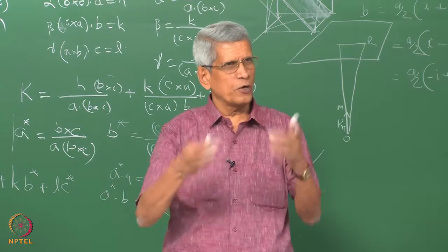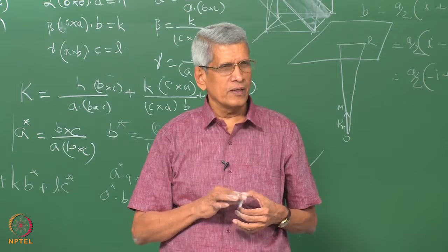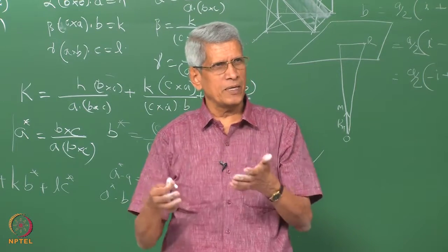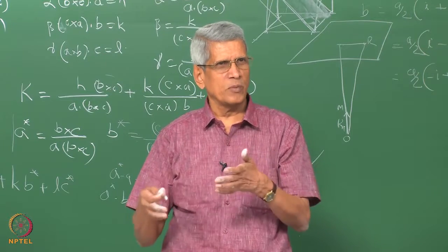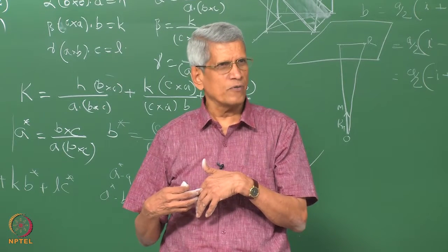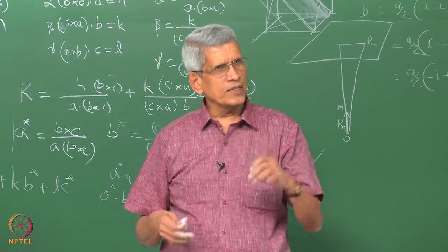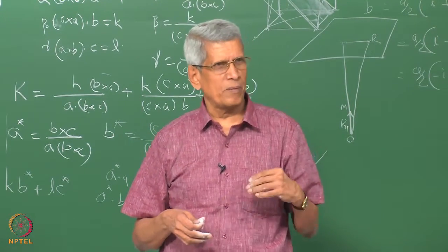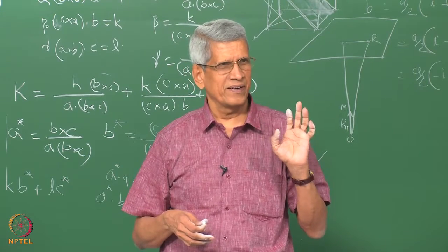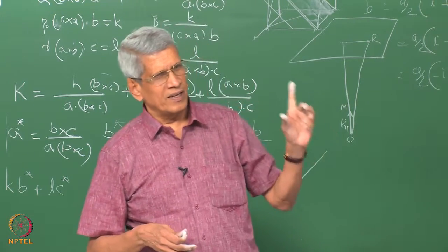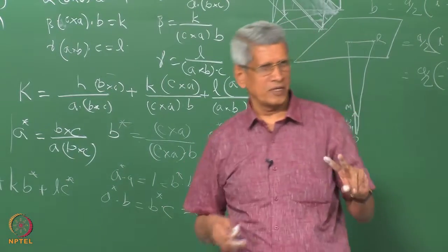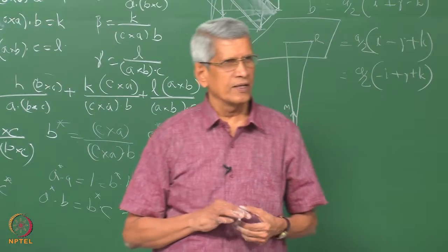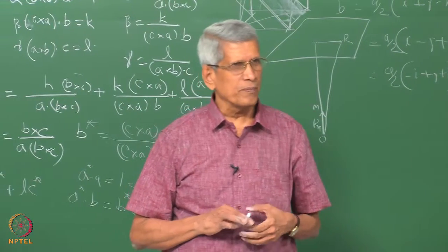There the units are going to be the inverse of that distance, whether it is millimeter, centimeter or nanometer. If we take the product of these two volumes, you can work it out as a problem, it turns out to be 1. That is, the product of the volume in real space and the volume in reciprocal space of the respective unit cells is always going to be 1.